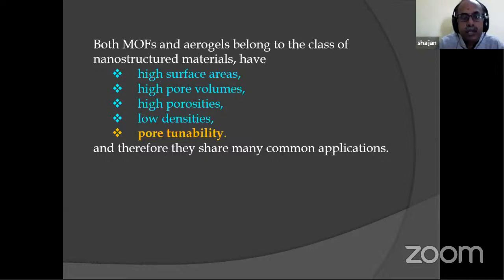classification of porous materials as well as nanostructures. And therefore, they have high surface area. If you say aerogels, they will have a surface area of around 300 meters squared per gram. If you take 1 gram of the material, their surface area will be around 300 meters squared. Whereas in MOF, it is still higher. It will be coming around 800 to 1000 meters squared.